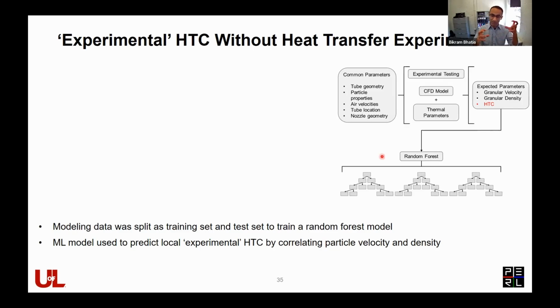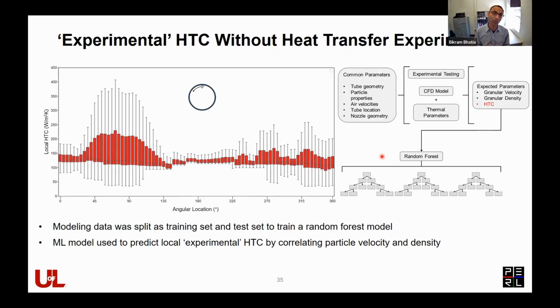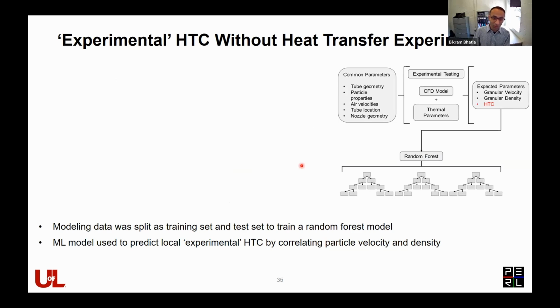And we trained a random forest model that essentially gave us a function that allowed us to map experimentally measured parameters such as the granular density and velocity that we had from our high-speed experiments. And we asked it to predict the heat transfer coefficient, which it did, which is shown in this plot here. And it looks pretty interesting. You see first that the magnitude conforms with what you would expect probably for fluidized bed heat exchangers, and also it is in accordance with the DDPM model, the high fidelity model that we ran for the same experimental configuration. But you see this asymmetry, which was not there really in our training data, that we see in the experimental result, which we were actually quite happy to see, because in our experiment, as I mentioned earlier,